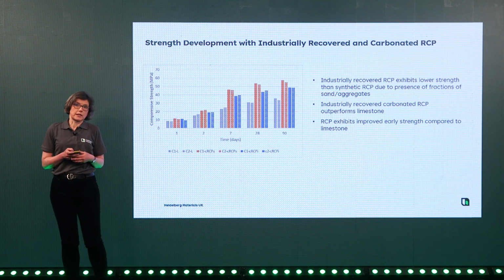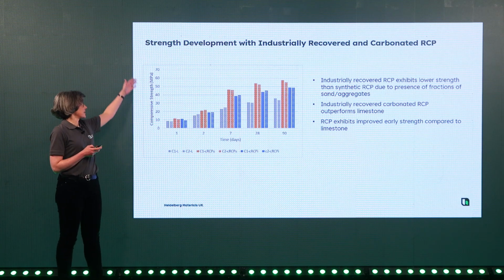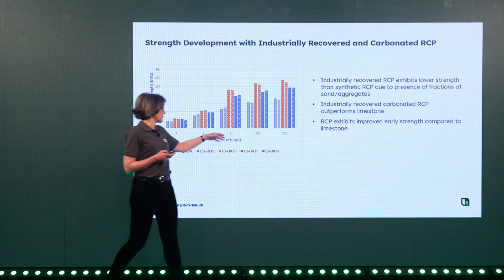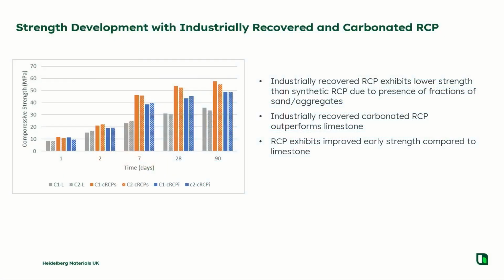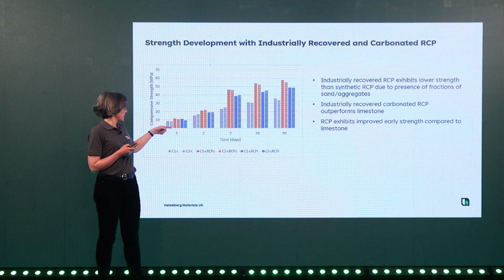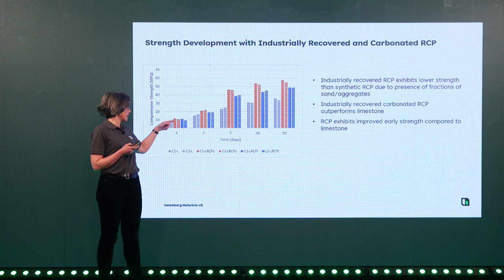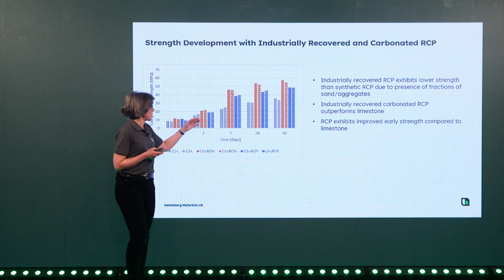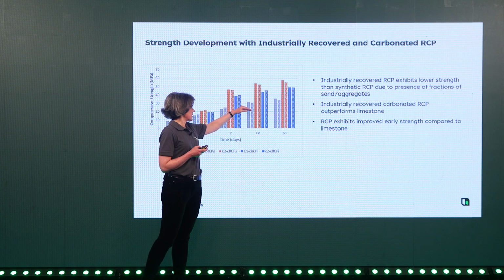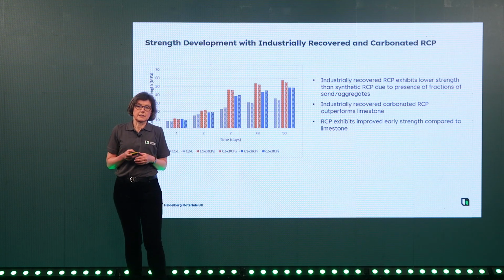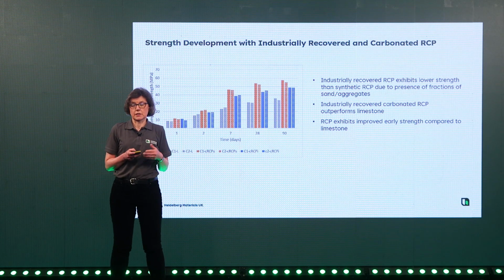And this is the one slide where I want to share some results. What you see here is a typical graph of compressive strength on the y-axis after 1, 2, 7, 28 and 90 days of cement mortar. We have made cements with 40% replacement levels in this case. The grey bars represent 40% replacement with just simple limestone fines. The orange bars are from synthetic recycled concrete paste, and then the blue ones are from these industrial trials which I talked on before. And as you can see, even at the very early age of 1 day, the carbonated RCP has a higher strength than using just limestone fines. And this becomes even clearer at 7 days and at 28 days, where there's a significant improvement in strength development, demonstrating that this recycled carbonated concrete paste is a true SCM with high levels of reactivity.